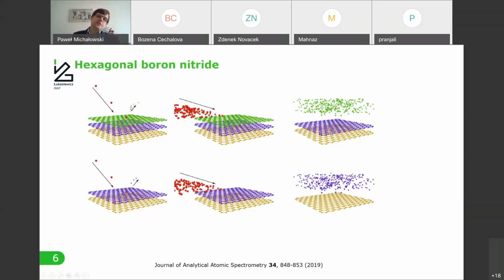And then I used a very short pulse with a little bit higher energy, but with a very high incident angle. And this pulse is used to remove the top layer. This is causing the preferential breaking of the weak van der Waals bonds between the planes without causing any damage to the underlying layer. So I usually call it something like ionic exfoliation. I completely remove the topmost layer of the boron nitride and expose the second one. And then I can simply repeat the same process.